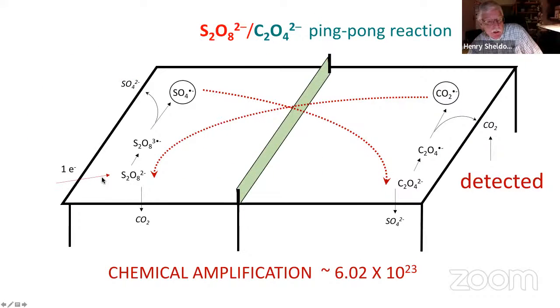You put an electron in. This is the player serving, this is the ruthenium hexamine, which puts one electron in to reduce persulfate. It actually goes through this unstable radical anion that very rapidly decomposes to sulfate and to the radical anion. The radical anion crosses the net. It oxidizes oxalate, which generates the CO2 and CO2 radical anion.